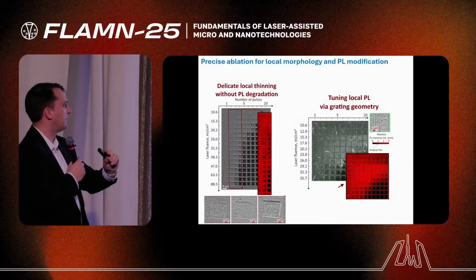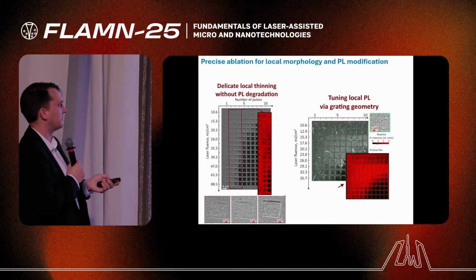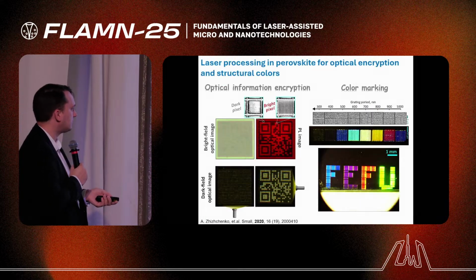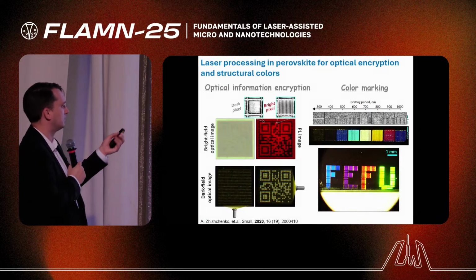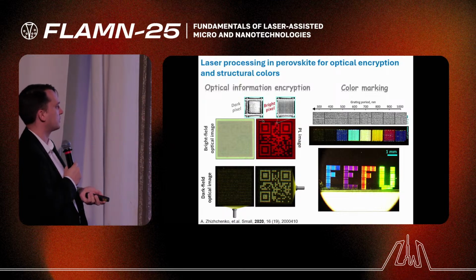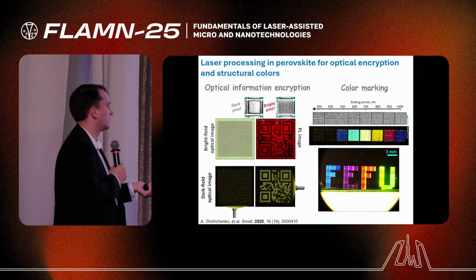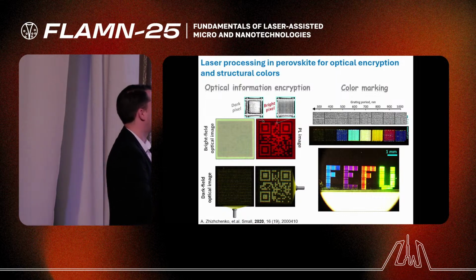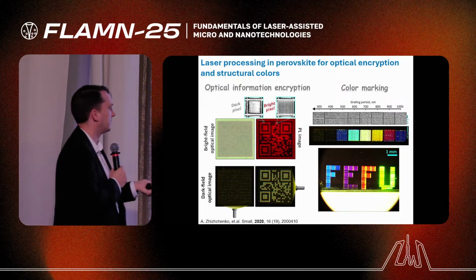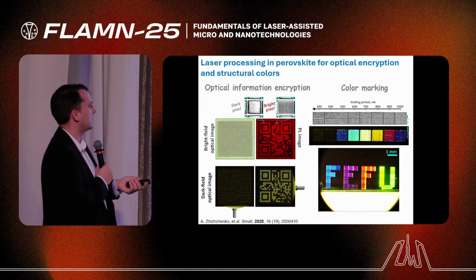And here it's useful also for thinning of the film. Here you see some example of how after each pulse we can make the film thinner and thinner and control the thickness. And also gratings can be fabricated, and such gratings can show nice diffraction efficiencies, which can be used for encryption. Let's say for different directions of light illumination, we have different patterns. So this is how it can work.